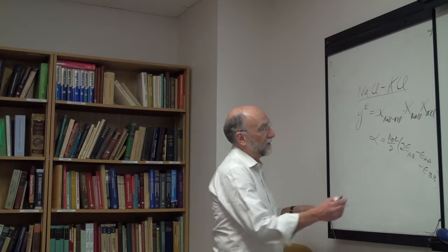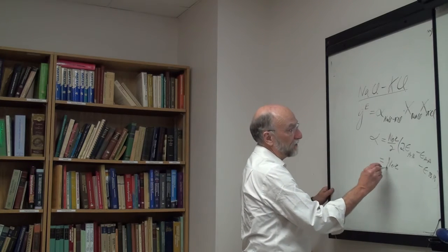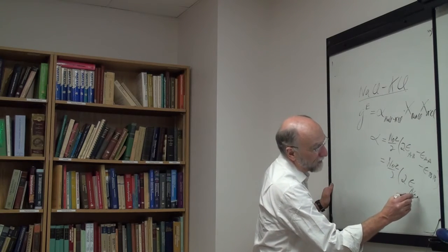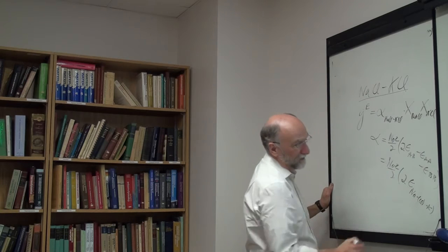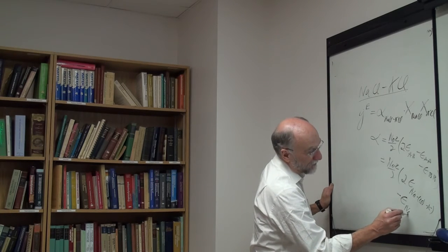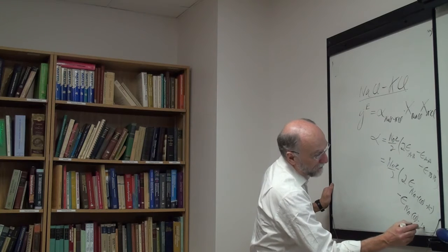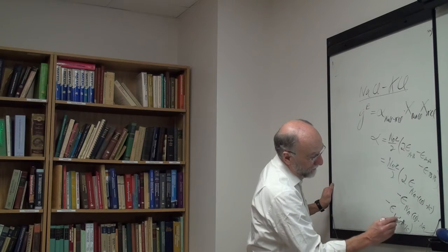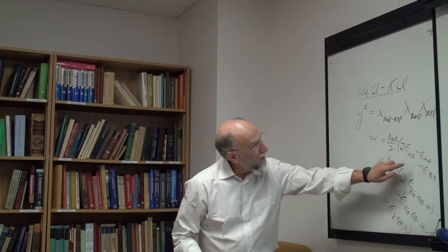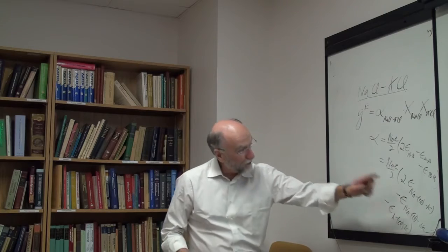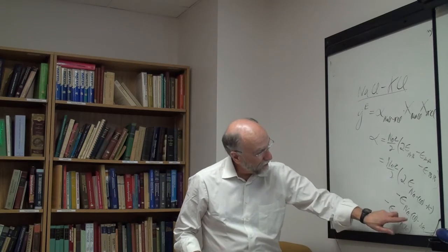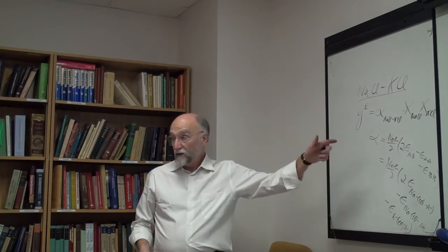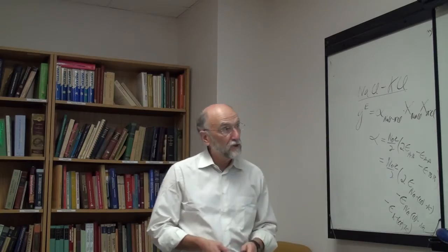Okay, the alpha here is n naught Z over 2 times 2 times the energy of a sodium-chlorine-potassium bond minus the energy of a sodium-chlorine-sodium bond minus the energy of a potassium-chlorine-potassium bond. So AB is sodium-potassium with the chlorine in between. AA is sodium-sodium bond, like you get in pure sodium chloride. BB is similarly potassium-potassium. These are second nearest bond energies because the first nearest neighbor bond energies don't change.